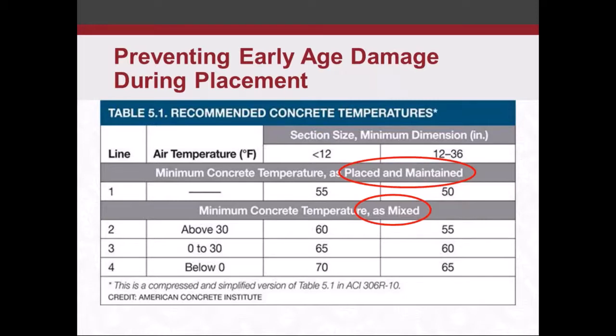We can maintain these temperatures a little bit lower. So generally speaking, we're looking at 55 degrees. We don't see a lot of structures that are greater than 12 inches. So 55 degrees is kind of that magic number, placing and maintaining. So that's placement at 55 degrees and maintaining a 55-degree temperature during our protection period.